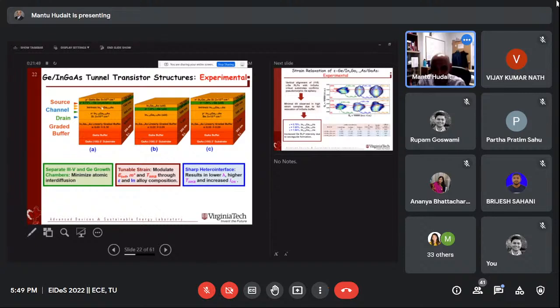You know, the game really starts when you want to put the top layer, and Professor Partha Sahu is the expert in the laser. I'm going to show you the data. You need a 1.5 micron to 2 micron thick layer on top of this thin 20 nanometer germanium. Please remember that this goes beyond my screen, that thickness you need. Bottom, no issues. Top is the scary part.